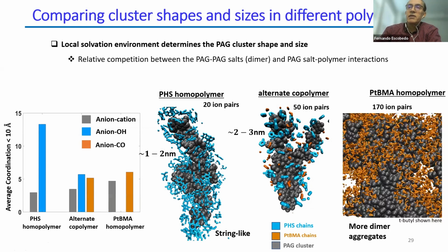But in contrast, if you look at what happens with the pure PTBMA, when you have these larger clusters, the gray bar, the interactions of the anion with the cation of the same salt, have increased so much at the expense of the interactions with the polar groups in the polymer. And this is really what's giving rise to this large association. Importantly, we also see differences in the morphology of these clusters. It's more string-like in the case of the PHS homopolymer, where the thickness of these strings is roughly order 1 nanometer. But by the time you go to the PTBMA homopolymer, it's more globular aggregates, which are much thicker, order 5 nanometers. So clearly, scenarios with a high concentration of PTBMA, like in this case on the right, will not be suitable for applications.